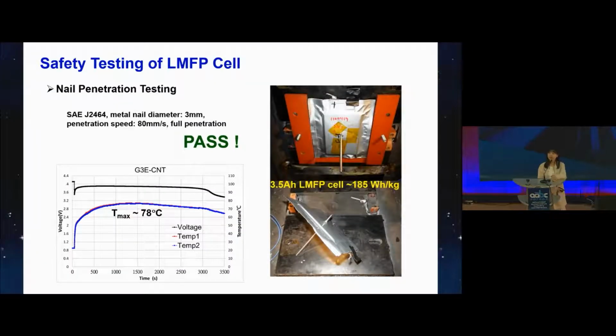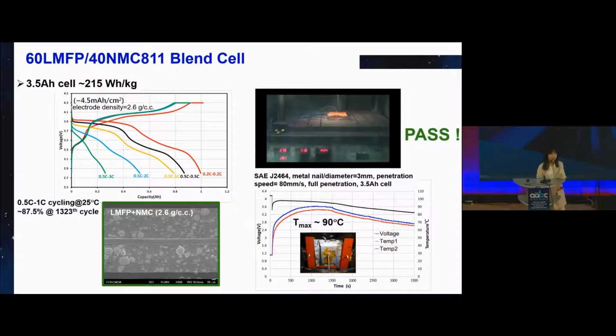To have a better understanding of thermal stability of LMFP, we also carried out the nail penetration test on both pure LMFP cell and also LMFP with NMC, the so-called composite cell, in which a regular PP or PE separator without ceramic coating was used. You can see that the LMFP cell passed the safety test with the maximum temperature about 78 degrees C. And we also have the 60% LMFP with 40% NMC811 composite cell, which achieves an energy density of about 215 watt-hour per kilogram. This cell also passed the nail penetration test with the maximum temperature of 90 degrees C.